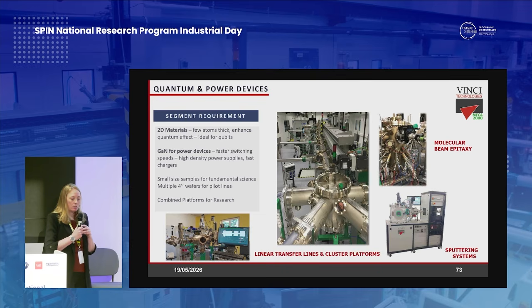With regards to this, as you know, we have the large 70-meter tunnel that's in Institut Jean Lamour, upon which we have several different equipments, over 24 systems or small systems attached to it, including the molecular beam epitaxy, E-beam, sputtering systems. We've grown a lot actually in the past number of years through these transfer systems. We now also integrate cluster systems, which you can see in the bottom left-hand corner. It allows us to incorporate XPS and STM systems quite easily onto the configuration.